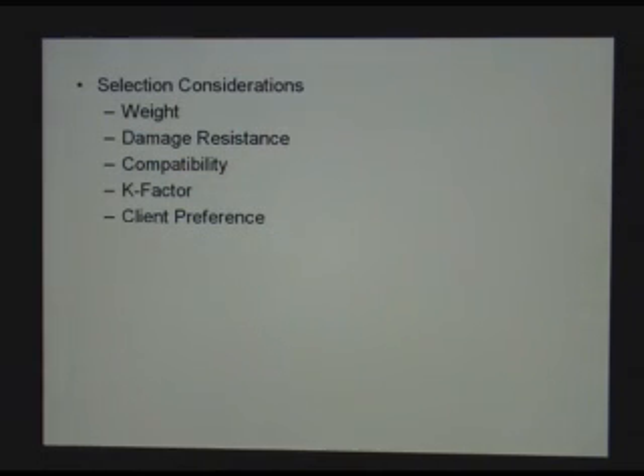When we select insulation, we consider the weight because it's a factor in the stress analysis of piping. Damage resistance, there are many cases that the insulation was damaged before the construction was complete. We make sure materials are compatible amongst themselves, but also compatible with the surface to be insulated. Very important, the K factor or thermal conductivity, which determines the insulation value of a material. And again, client preferences. Clients have their own opinions about what to use and not to use.